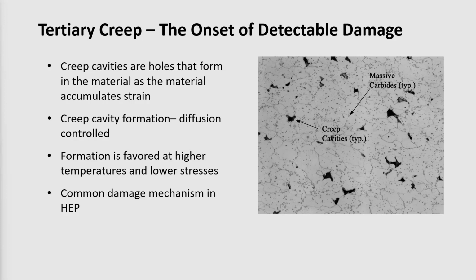All right, so in any case, early stages of the damage will show up as small microscopic holes in the material. With progression of the damage, you'll see more of these cavities develop. Ultimately, they'll begin to link up to form microfissures. And with additional accumulation of damage, you'll get macro-cracking and failure of the component. So the challenge here, as you can imagine, the particular micrograph that you're looking at, the original magnification was roughly 500 times. And so the challenge for any kind of inspection is to find this kind of damage as early as possible.